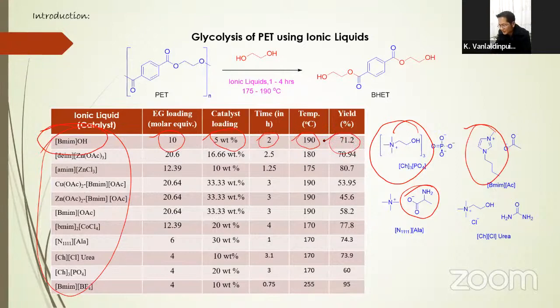And the best result is obtained with Bmim BF4. This is 1-butyl-3-methyl imidazolium tetrafluoroborate. Okay, and the reaction gives 95% yield in less than 1 hour, but the reaction temperature is 255 degrees Celsius, which is quite high.